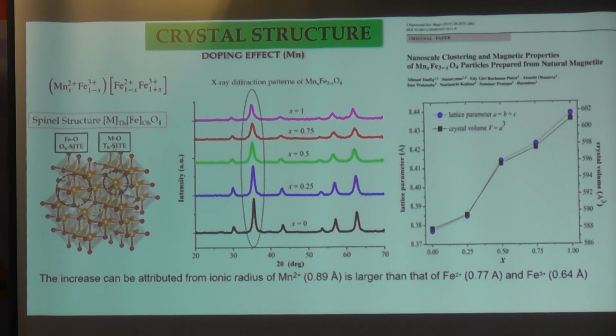The second one, because Mn has a higher magnetic moment, 5 spin, and Fe is 4 spin, so theoretically the magnetization will increase about 25% only by replacing one atom of Fe by Mn. So it will make the application of magnetite increase significantly. This is the lattice parameter. The higher the Mn composition, the higher the lattice parameter, because we know that the ionic radius of Mn is 0.89 angstrom, larger than Fe2+ and Fe3+.